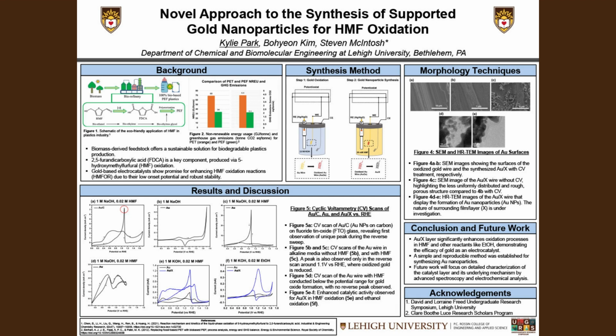Our research contributes to this transition by enhancing the production of FDCA, the building block of PEF. FDCA is synthesized from HMF oxidation, and we focus on gold as a catalyst for this reaction due to its efficient and stable nature. We specifically chose gold as a catalyst based on a unique observation from a cyclic voltammetry, or CV scan, of gold on carbon nanoparticles coated on fluorine tin oxide glass in 1 molar sodium hydroxide with 20 millimolar HMF, as shown in Figure 5a.